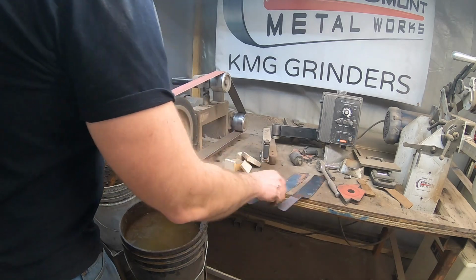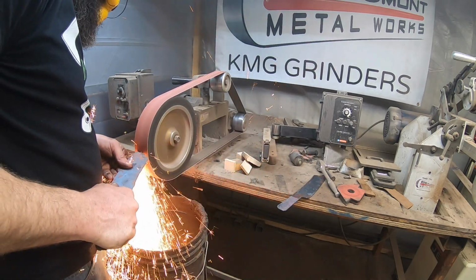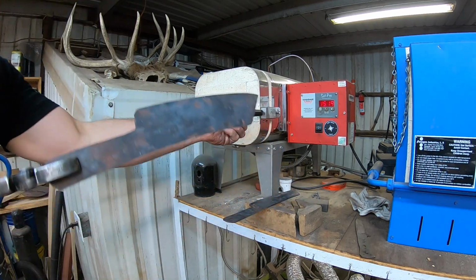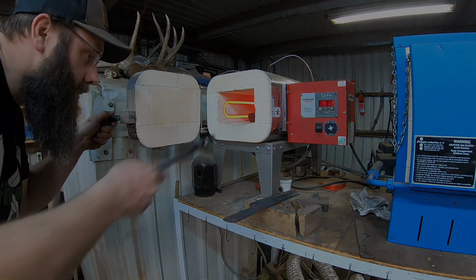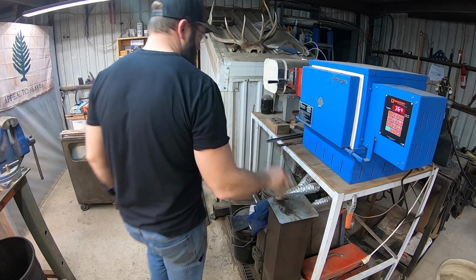I will say that forging closer to finished dimensions is kind of growing on me a little bit. It negates any need for rough grinding, which is something I typically have done in the past, and also depending on the project, such as maybe a Damascus blade where you want to leave the steel on until the last minute. But in this case, I got the spines forged down to about 100 thousandths, and that's a pretty good thickness, and they're going to stay that thickness, and the bevels a little thinner, about 60 thousandths, I think. So it's kind of nice.